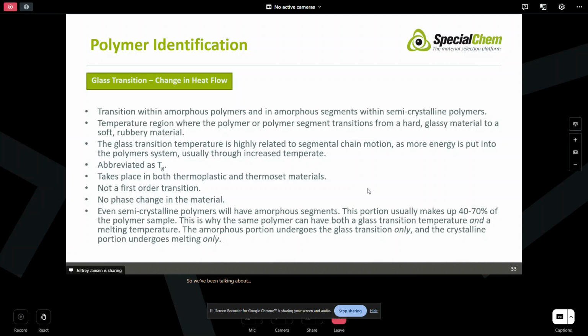So we've been talking about melting transitions, melting endotherms. Well, again, the other primary transition, if we're talking about an amorphous material, is going to be a glass transition, which is a change in the heat flow. Okay, it occurs within amorphous polymers and in the amorphous segments within some semicrystalline polymers. Now, oftentimes that glass transition is relatively weak in some materials. For example, polyethylene, it's so weak because it's a very crystalline material. Polypropylene, kind of the same way. It's hard to see that glass transition. But they are present for semicrystalline materials representing the amorphous state. It's the temperature region where the polymer segment transitions from that hard glassy material to a soft rubbery material. That's why we call it a glass transition. That makes some sense. Again, it takes place in both thermoplastic as well as thermoset materials. So thermoset plastic will also have a glass transition.